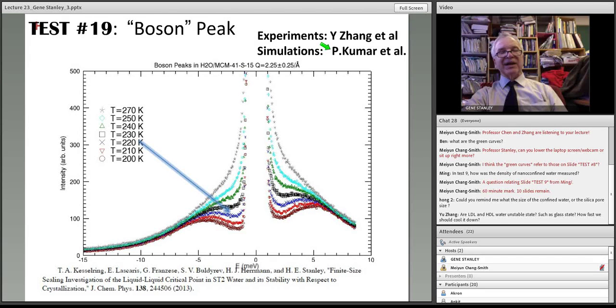There opens up a second sideband here, and this second sideband is presumably, we interpret or hypothesize, a consequence of this liquid-liquid transition. And the reason it's a consequence is if you have a rigid second phase setting in, then you'll have new vibrations characteristic of this second phase. And that's the interpretation. The experiments were started by Yang Zhang and Meng and others in the Chen group, and the definitive experiments are going to be done shortly. So stay tuned, and you'll probably see a famous paper coming out in a number of months from now. I think the experiments are scheduled for fairly soon. Neutron experiments.